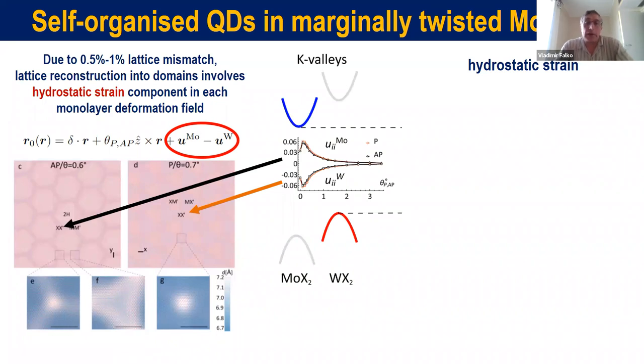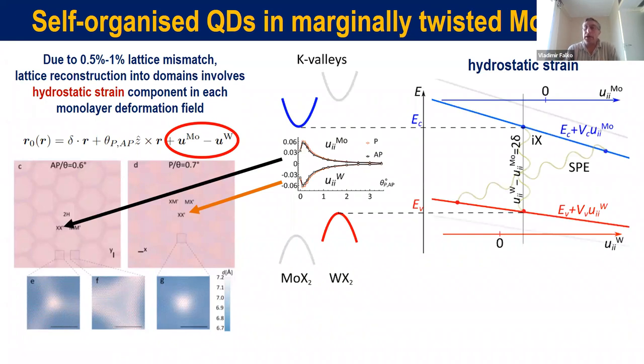Well, then why is this hydrostatic strain so important? Well, first of all, because it appears to be quite large in those corners, reaching several percent of strain. And the reason why we care about it is because when we look at the evolution of bandgaps in the material as a function of strain, of hydrostatic strain, shear strain does not do much, but hydrostatic strain changes the bandgaps quite a lot.